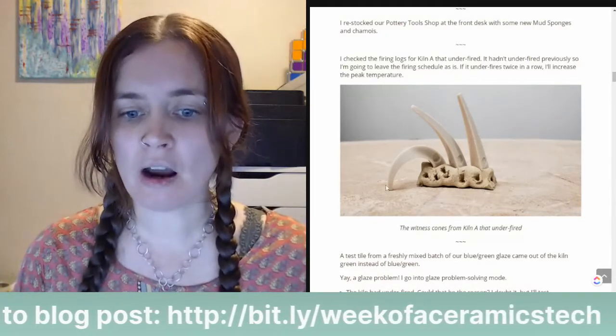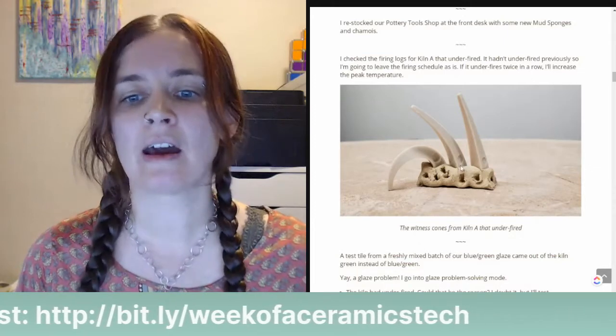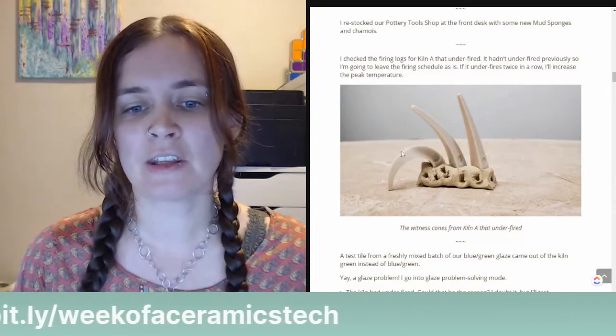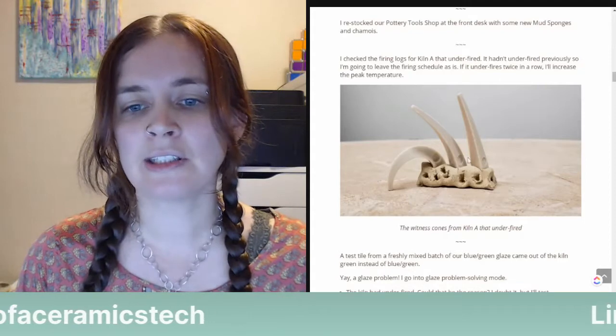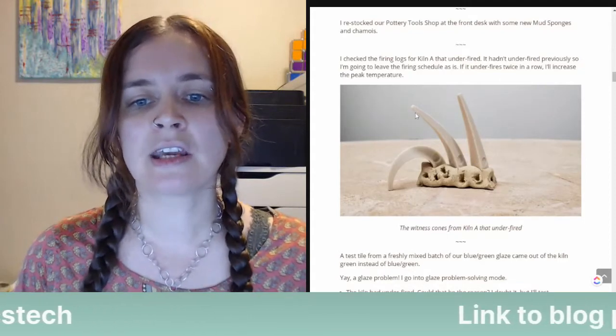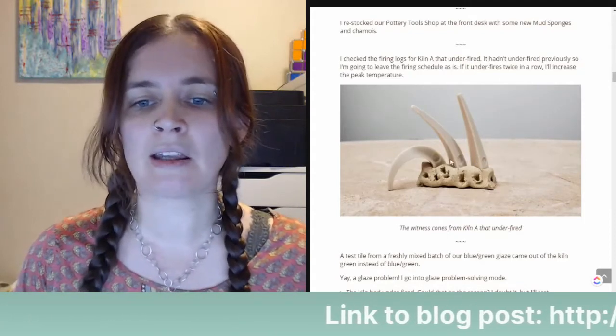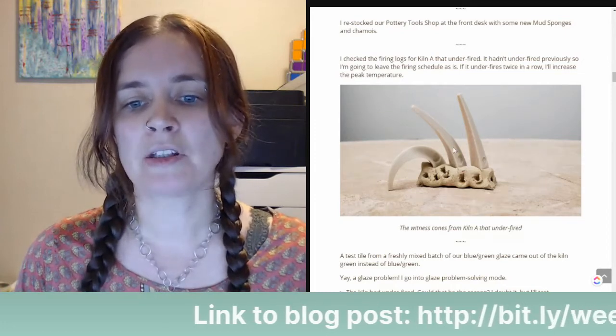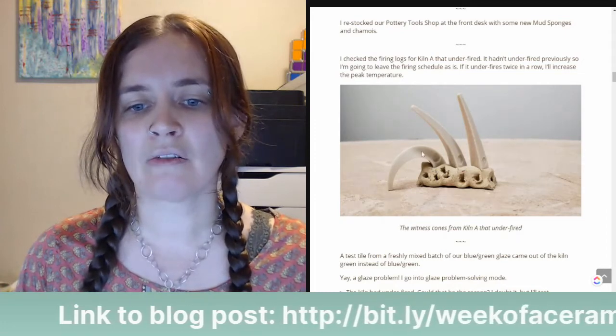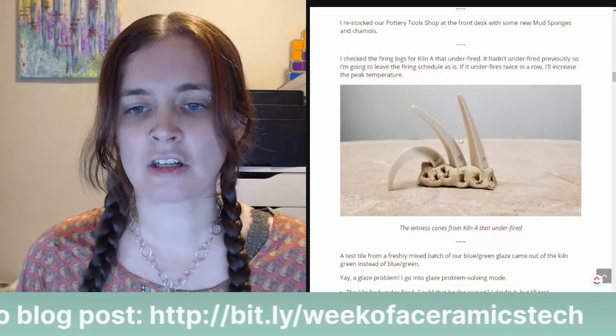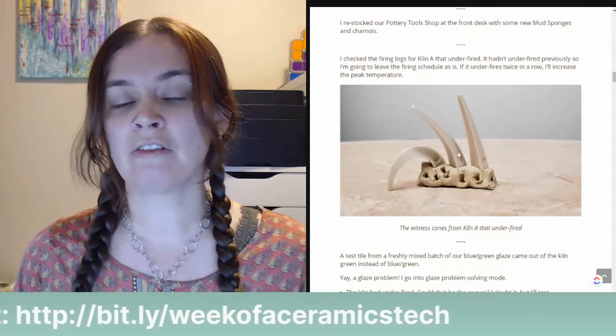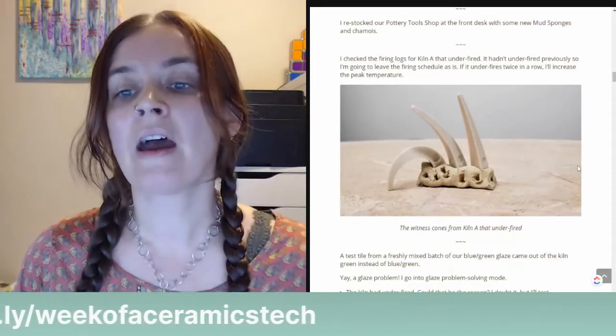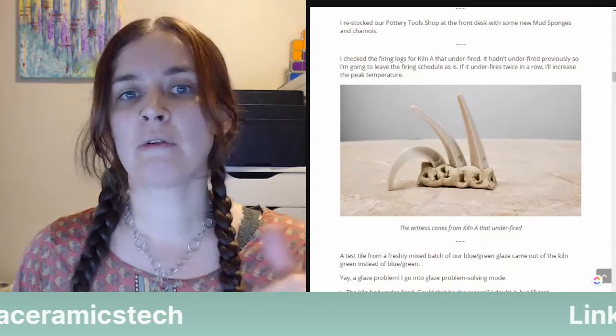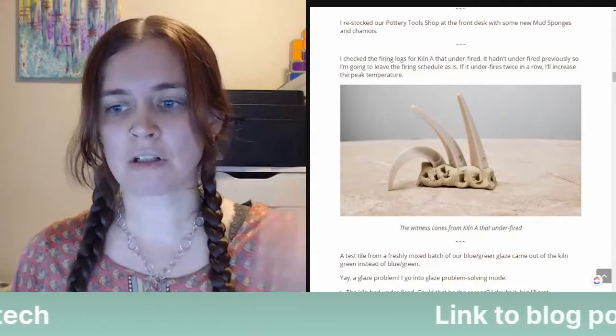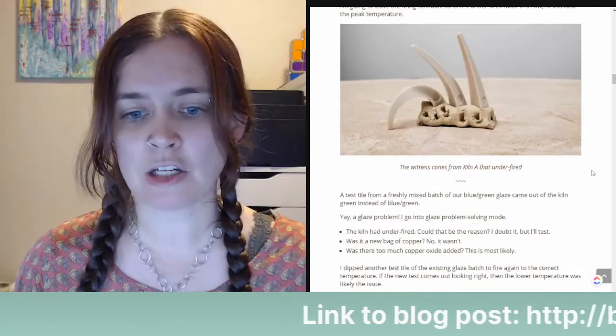And so these are the witness cones from kiln A that had underfired. So this is cone 5, this is cone 6, and then cone 7. You can see cone 6 is just barely starting to bend. I want cone 6 to look like cone 5 over here pretty much. So I would consider that underfired. So we keep track of that. If it happens twice in a row, then I would increase the top temperature of our firing schedule.